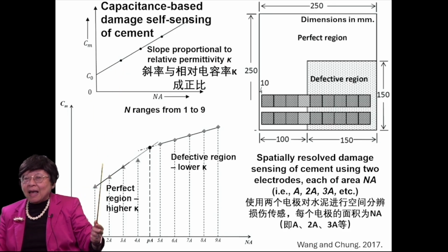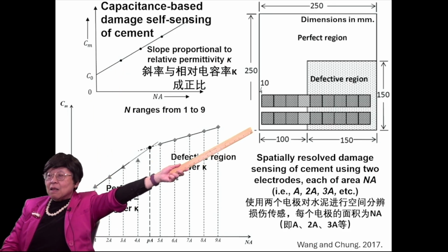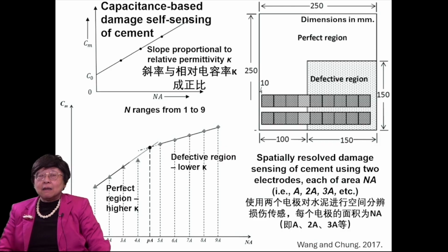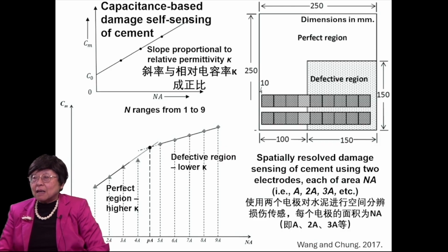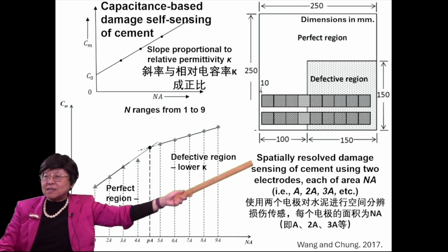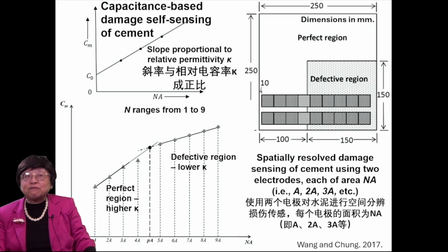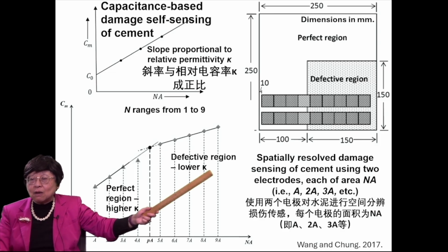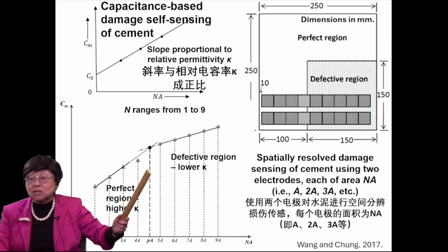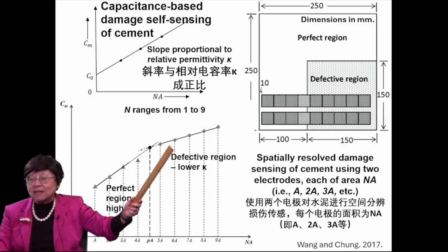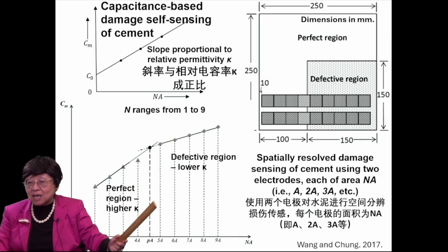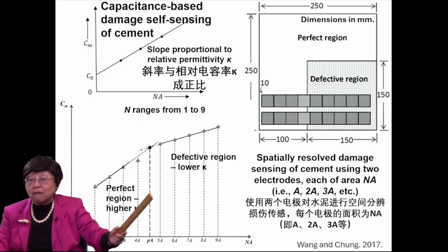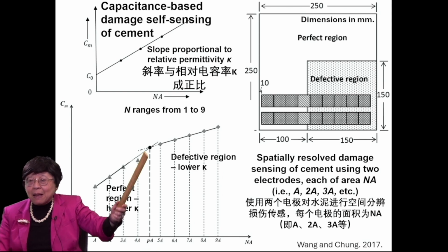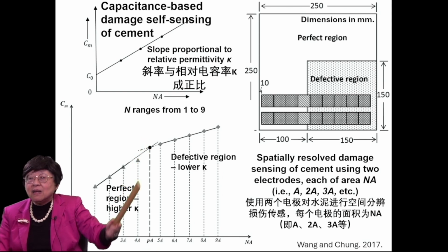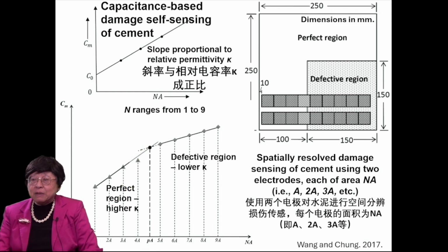Here we have the left part of the material, the cement, is perfect. The right part is defective, and the defective part has lower permittivity, which I call kappa, and so the slope is less for the defective region. So we can see the place where it changes slope, and that place corresponds to where the interface is between the good and bad regions.